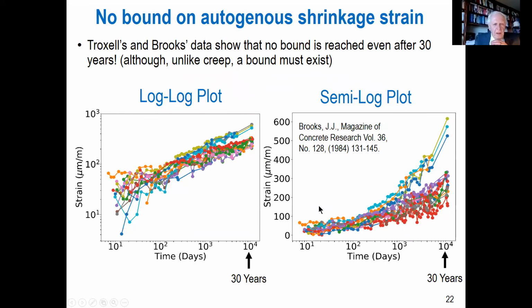All right. So the next effect is that the self-desiccation causes shrinkage, and that's called autogenous shrinkage, happening by itself. Now, I will comment later, it is not caused directly by the chemical reaction, but as a consequence of the decrease of humidity. This was known for a long time. Troxel in 1950s and 60s measured that for concretes with relatively high water cement ratio, where the effect was not so pronounced, and later Brooks in Leeds measured